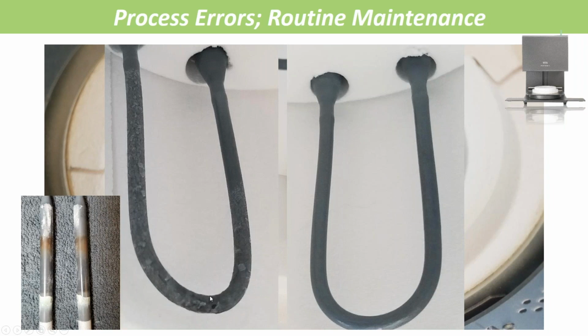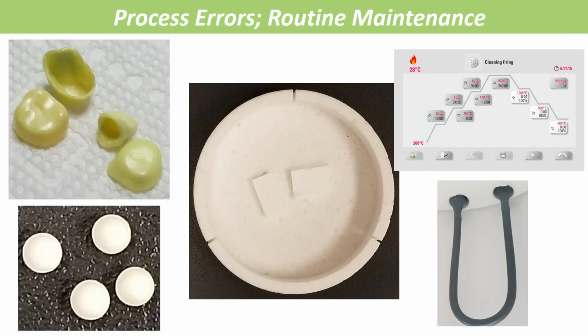And by cleaning it without anything inside the sintering process, what you're trying to do is shake off all those oxides, all that material that's collected on this, and try to refinish it. You actually have microfractures inside these used elements, and by doing a clean cycle, the material will actually kind of heal, and the micro cracks will get smaller, and therefore you get a longer lifespan of your sintering furnace. So if they're contaminated, if you see that, you have to do that clean firing.